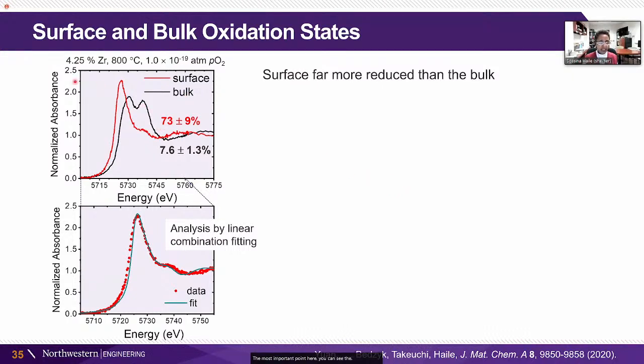You can see that in this particular measurement, this is for a 4.25% doped zirconium, high temperature, very reducing conditions. We can see that the surface looks much, much more like that cerium 3+ reference spectrum that I showed you compared to the bulk. The bulk looks very much like that 4+ reference spectrum. And we do the analysis by linear combination fitting so that we can quantify the cerium 3+ concentration. And you can see here, it's about an order of magnitude difference in terms of the extent of reduction at the surface versus the bulk. So the surface is far, far more reduced than the bulk.